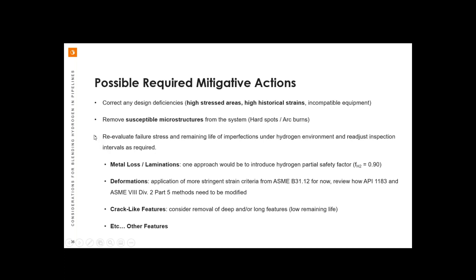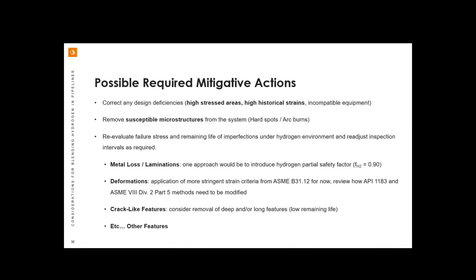And of course, reevaluating all of our failure stress and remaining life for hydrogen service. And we noted that for metal loss, we may need to introduce an additional partial safety factor. For deformations, it seems like perhaps we can continue on the same path of performing strain assessments with caliper or using FEA to get our strain and simply comparing those strains to new strain limits. All right, back up here. For crack-like features, we may have to remove certain very deep features or very long features out of the system because of low remaining life. And we may also have to pay close attention to pressure cycling.